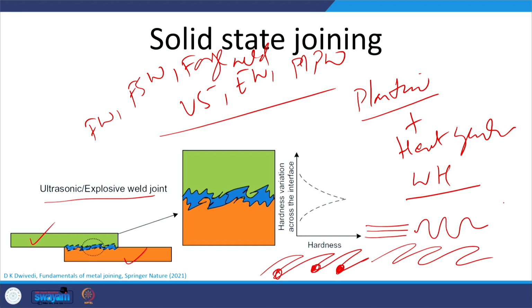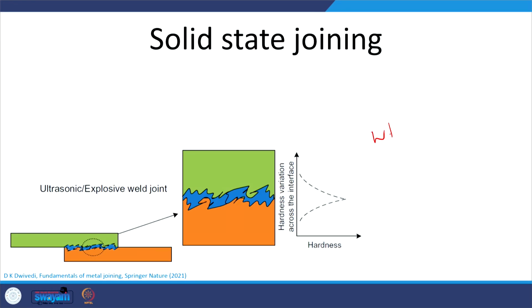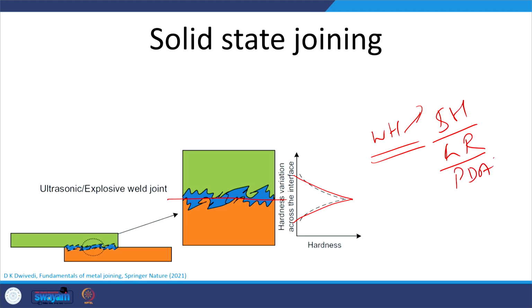So, but in all these cases what is common? Significant plastic deformation at micro level, okay, and when this plastic deformation occurs in the work hardening metal, then there is a significant increase in the hardness. Okay. So, this can be due to the simple strain hardening, the grain refinement or the plastic deformation assisted transformation. So, multiple factors can be responsible for the slightly higher hardness, because the heat generated during the ultrasonic and explosive welding is very limited.